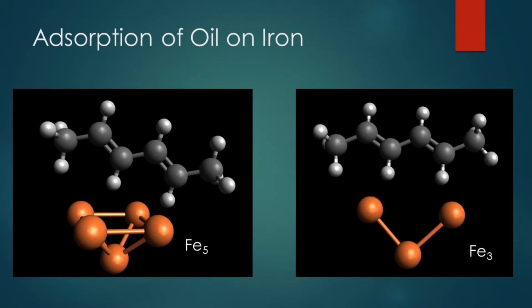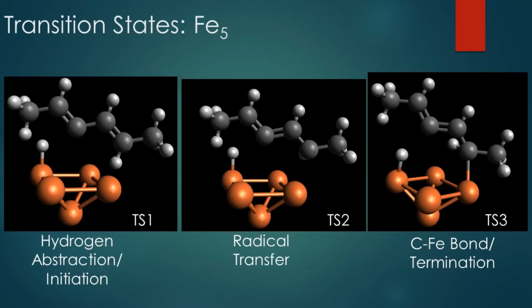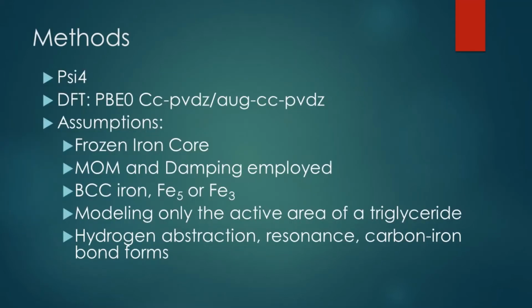The states I chose to investigate are the iron and oil by themselves, in the absorbed states, and a potential reaction that begins with the abstraction of a hydrogen, TS1, the movement of a radical to an adjacent carbon, TS2, and finally, bonding between the carbon radical and the iron surface, TS3. After geometry optimization, the single point energy of each molecule was determined using density functional theory at the Perdew-Burke-Ernzerhof 0, or PBE0 level, with an augmented cc-pVDZ basis set.